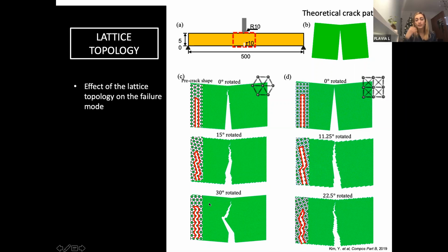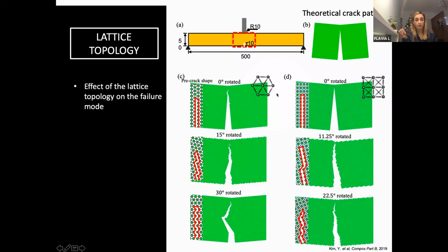So basically, there is also this effect that we have to take into account. This one is more affected by different orientation. In our previous work, it worked better, but we need to be careful and take into account the presence of different lattices when we want to model these kinds of materials. That would be useful, especially when we are working with materials which have, for example, nanoparticles inside, or aligned nanoparticles, or some specific intrinsic anisotropy.